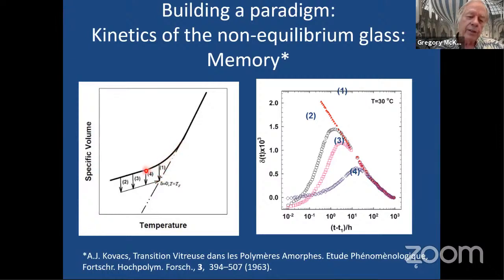But for these other ones, what he would do is he would stop, age partially to equilibrium, and he spent a lot of time figuring out how that when he jumped back up, he got to where T equals TF, or the departure from equilibrium should be close to 0. And then he sat there. And if you had a single relaxation time process, you shouldn't get the memory effect, at least in the models that we use. And it should be monotonic.